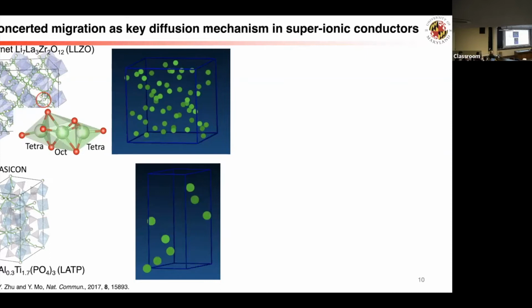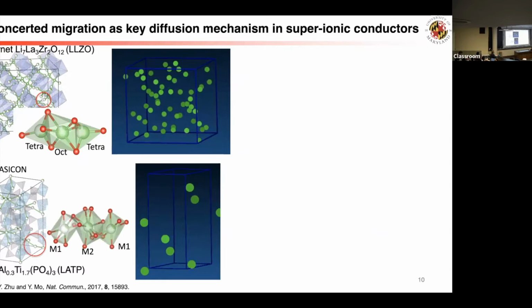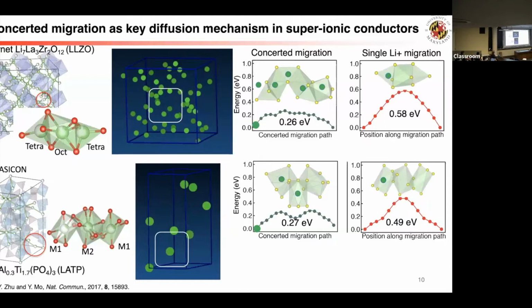But basically, different from the animation before, where you have a single lithium jumping, if you look at these super-ionic conductors, they have multiple ions jumping at the same time. We think this is a mechanism we call concerted migration. Multiple ions jump at the same time, and this actually gives a lower energy barrier. As we evaluate more using DFT energy barriers, if you have 5 lithium moving together, you would only have this low barrier of 0.26 eV. But if you only have 1 lithium ion moving, it has a barrier of about 0.6 eV.